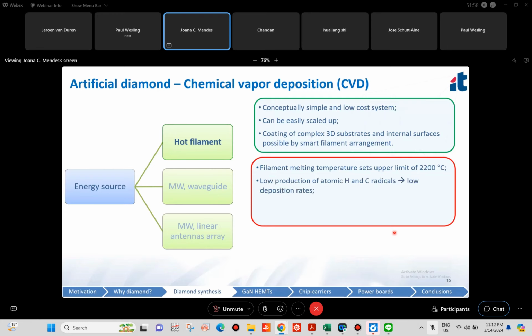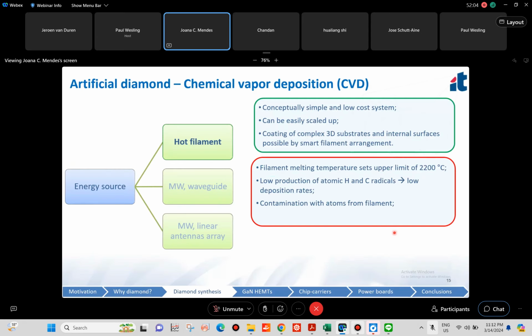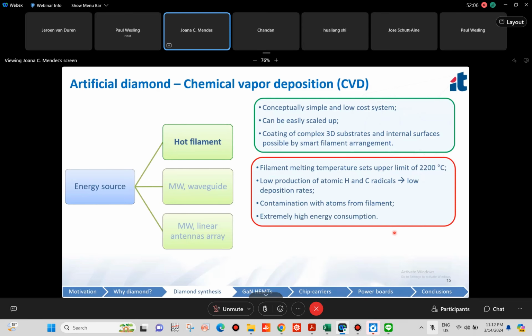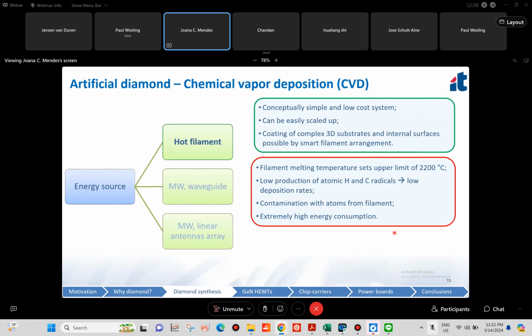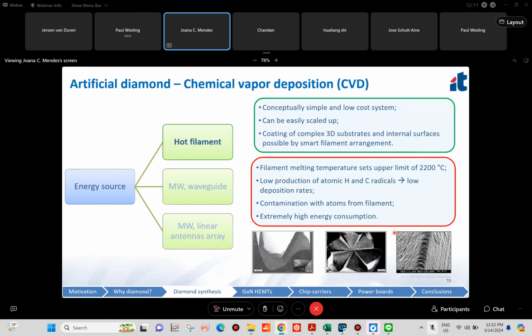But then we have a low production of atomic hydrogen and carbon radicals, meaning that we have low deposition rates, we have contamination with atoms from the filament, and last but not least, we have an extremely high energy consumption. So typically these systems are only used for tribological applications.